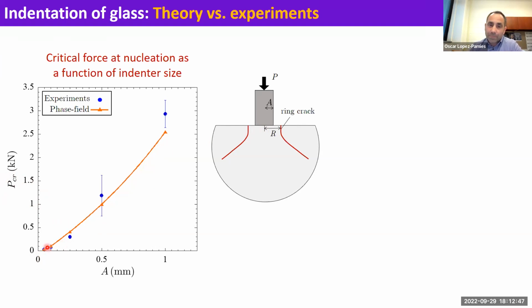But one has to be careful, because if you make the indenter too small, the indenter typically is made of a metal. The metal will have plastic deformation. That means that it will deform, the area will increase, and you will not be here, but you will be here. So there is a balance: if the indenter is not very strong and is going to have plastic deformation, you will never be able to break the glass if the indenter is too small, because it will deform and you will never break it. But if you manage to have something that is not going to deform, the smaller the indenter, the better, because a smaller force will give you nucleation. And once you have nucleation, the glass will just propagate the crack and you will break the window.